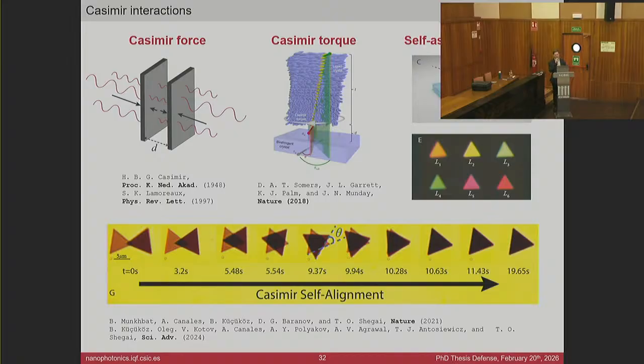Well, in our coupled dipole model, we couple the nanostructures, our electric dipoles, through the Green tensor. And once you have a substrate, this Green tensor will be modified because you will have a contribution from the reflection from the interface of your substrate. And in this way, your calculations could change.